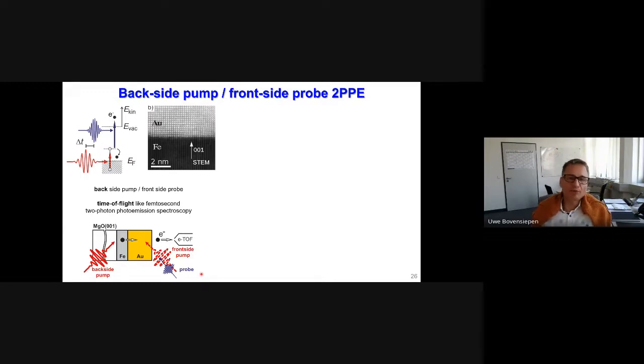Now, how do we analyze this? Well, we do a pump-probe experiment. We excite at the back side, and we probe at the front side and detecting now photoelectrons. So we do 2 photon photo emission. We pump electrons in the vicinity of the Fermi level in iron, and we probe electrons on the gold surface at the other side of the sample. So this pump process is basically including the injection across the iron-gold interface, and you see here the nice epitaxial structure in this electron micrograph image.